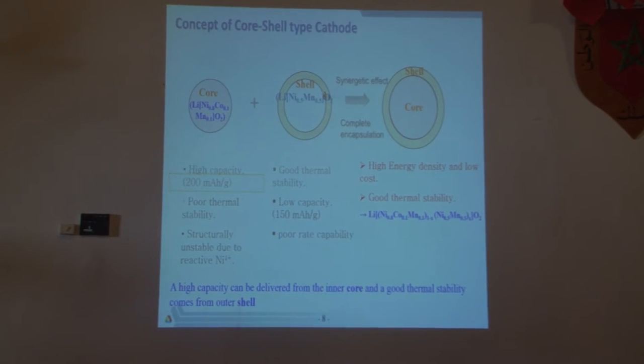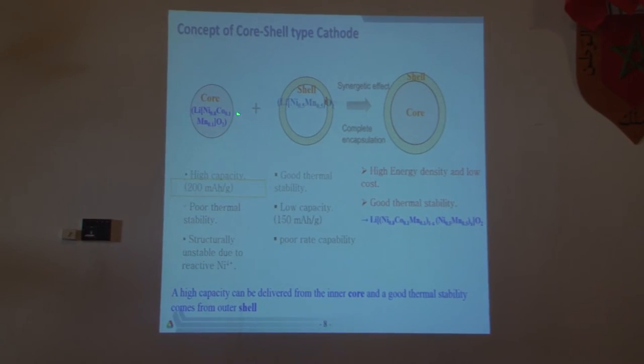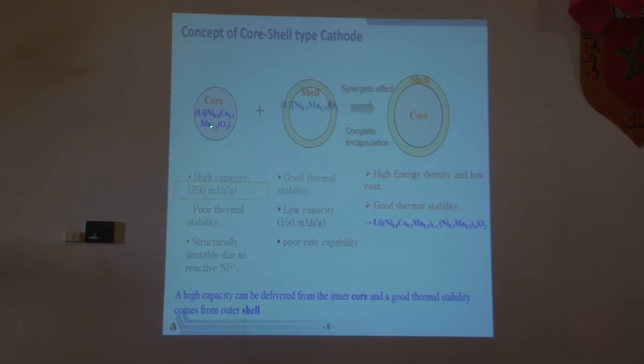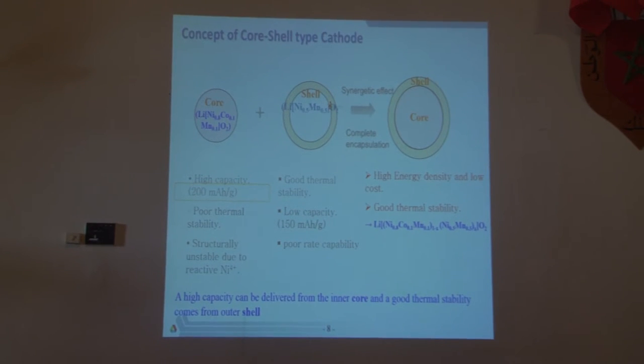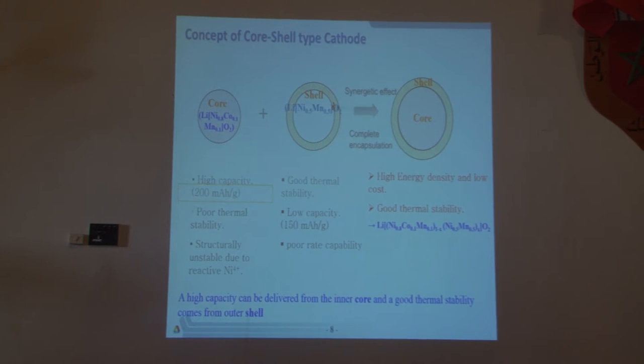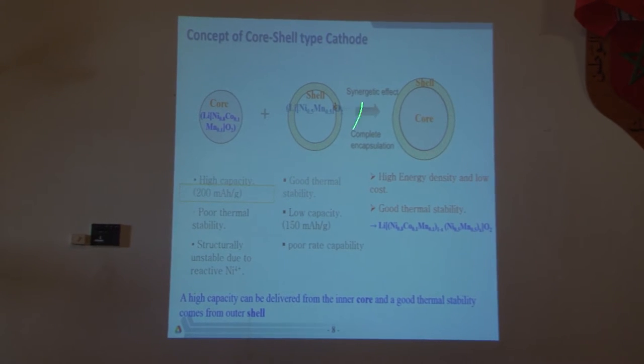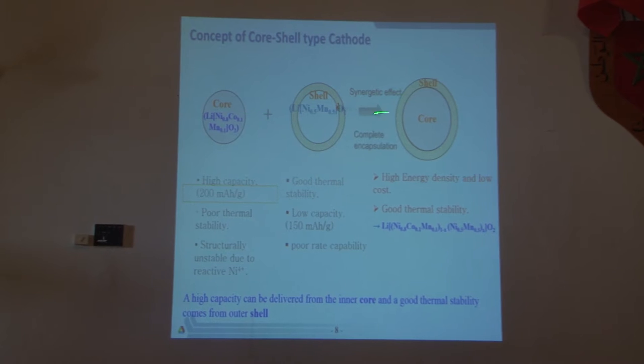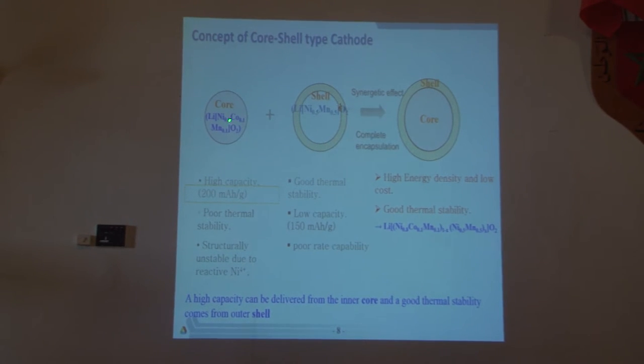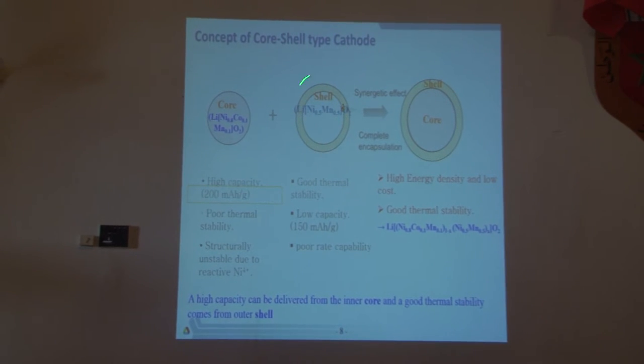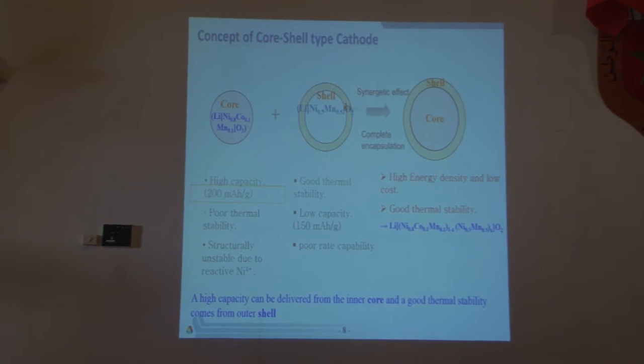So the first step could be, for example, you can use a core which is nickel-rich, and then, as we know, manganese is much more stable. It can be stable in manganese 3, 4+. You can put a shell on top of that, so you end up with a core shell like this. So you take advantage of the nickel-rich for high capacity and manganese-rich at the shell for stability.